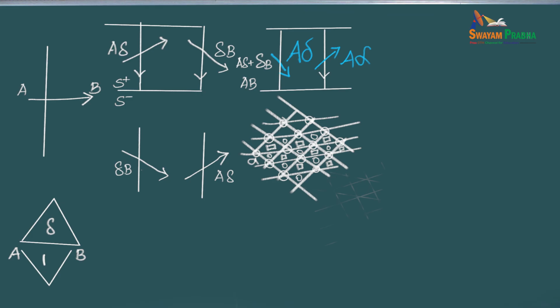That's the stacking fault. So actually, you don't have the choice for the front, the first partial. The first partial is when you dissociate like this. The first partial is the one that transforms a plane in the stacking in the plane above. Because the other one will transform the stacking in the plane below, and that's putting atoms on top of one another, and that's energetically completely unfavorable. You see what I mean? So the simple rule that you'll find in some of the old books is that for this reference configuration, you put the Greek letter on the outside.